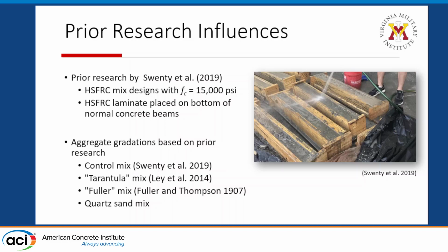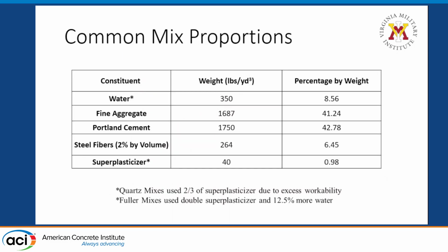This photo is from the research completed in 2019, with the legs of Dr. Swenty right there. These were the mix proportions used in my mix and the research completed in 2019. All these materials were locally available except for the steel fibers, which were purchased from Dramix. It's important to note that the Fuller mix required additional water and superplasticizer, and the quartz sand mix required less superplasticizer, just for proper workability when I was trying to flow these into their cubic molds.